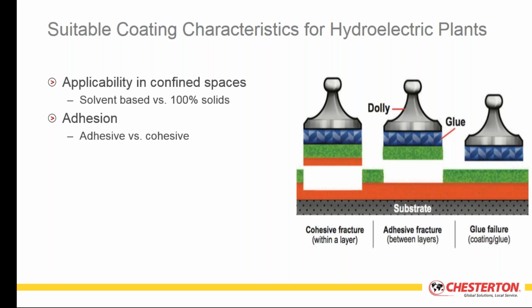And the nice thing about these epoxy-based coatings is they're easily repaired and restored in place. It's not a very complicated process. Effectively, dry the area, roughen it by mechanical means, ideally power tool, remove any debris and residue left on the surface, then apply additional coating to the prepared area and allow it to cure. The curing process can take some time—anywhere from several hours to a day or so, depending upon the temperature in the application area.